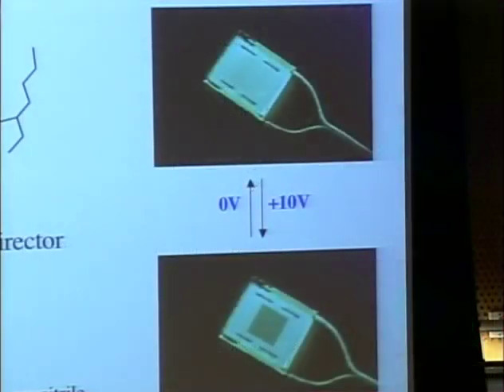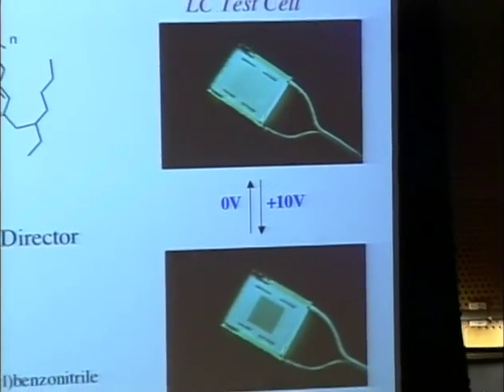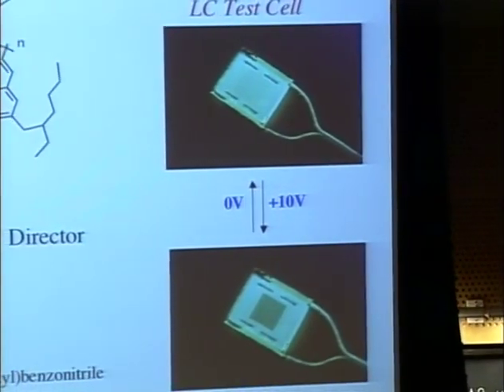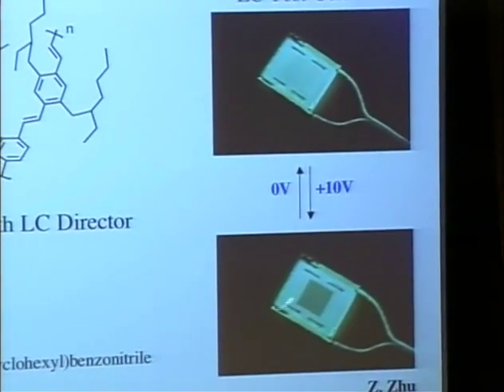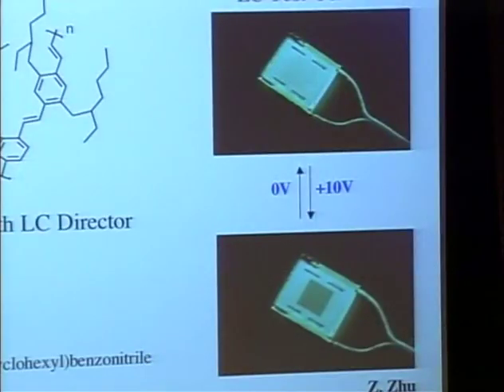Without a potential on it, the molecules are aligned in the plane of the screen. When you apply a potential over these little pads that are defined by indium tin oxide, the molecules rotate out of the screen and they're pointed straight at you. There is essentially no transition moment in the plane, so the molecule cannot absorb light, and therefore it can't emit, and that's why you see this going dark. So you can do this,